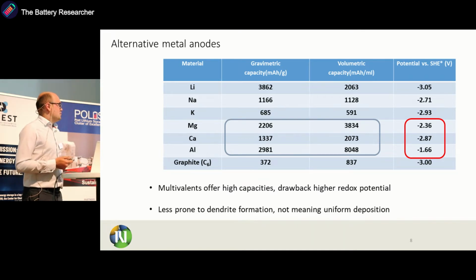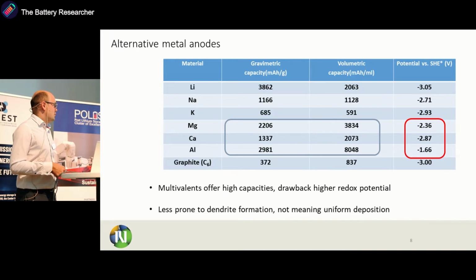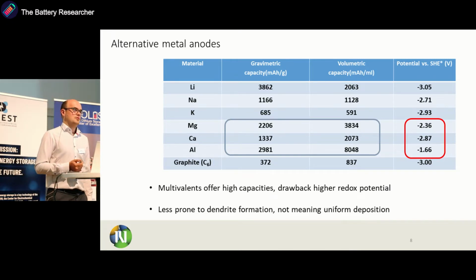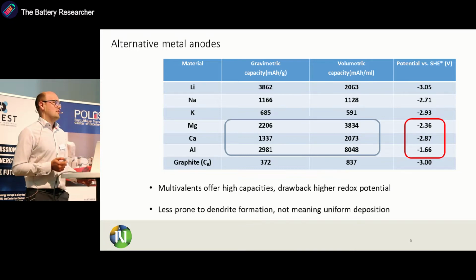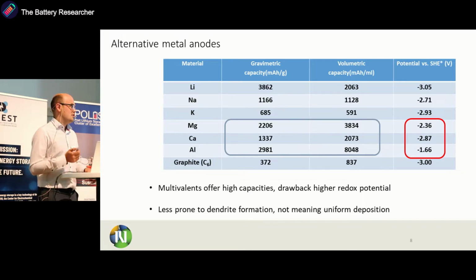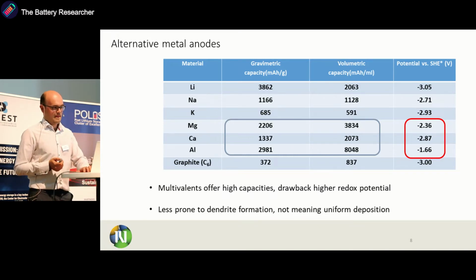Another important thing to consider is that while the multivalents are less prone to dendrite formation, this does not mean uniform deposition. So if you read in many articles that magnesium deposition is non-dendritic, don't assume uniform deposition. You should always check how it is going in each specific electrochemistry condition and in specific electrolytes.